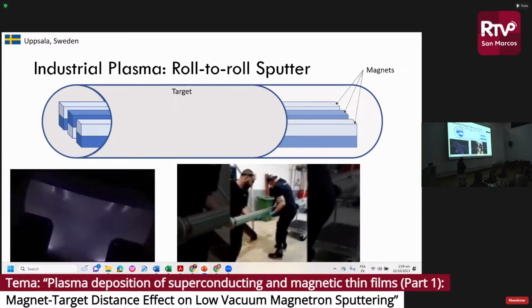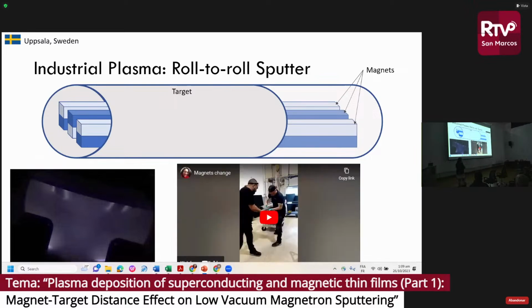So this is how the magnets are positioned inside the target. The target is actually a cylinder, and then you have magnets which are oppositely facing. There are 3 sets of magnets. The middle one is oppositely facing so that there's going to be a confinement in the middle. And if we would like to change the target, let's say from nickel to tungsten, we have to take away the magnet and then replace it with another target. And to do that, we actually need a couple of guys to move the set of large magnets.